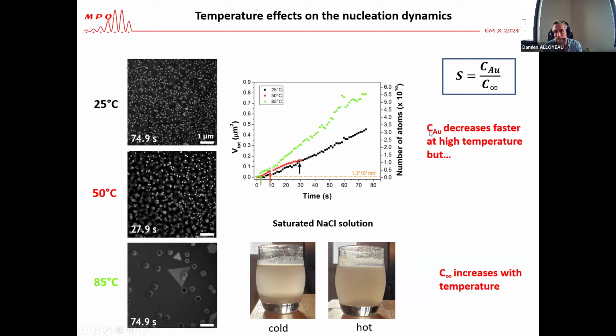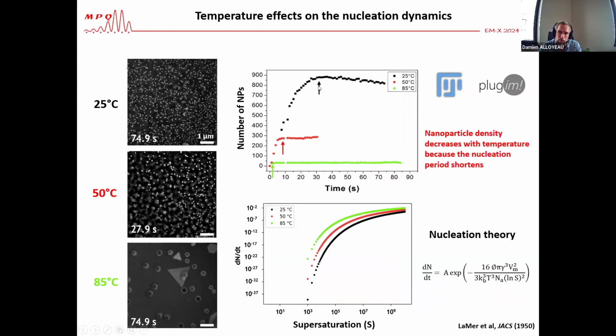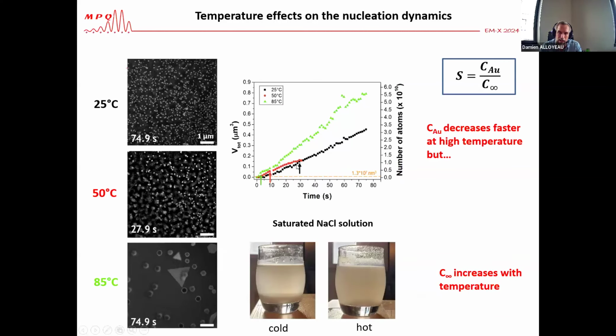So yes, it seems that the gold concentration decreases faster at high temperature, so you're happy, meaning that your supersaturation decreases. But now when you look at those arrows that correspond to the end of the nucleation period, you realize that, in fact, you have much less gold that has been consumed at 85 degrees at the end of the nucleation period than at 25 degrees. So it doesn't match anymore.